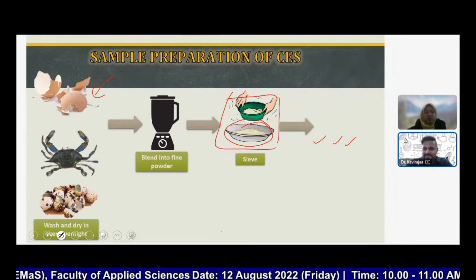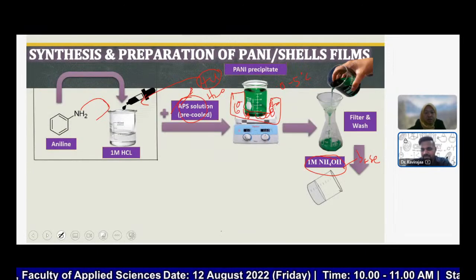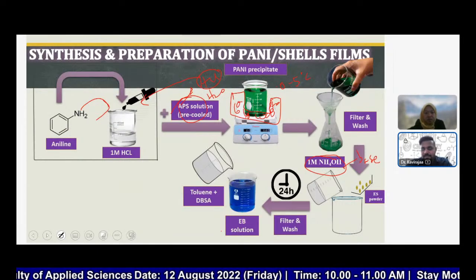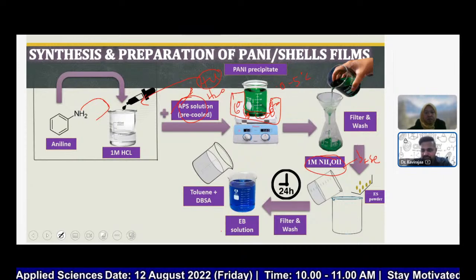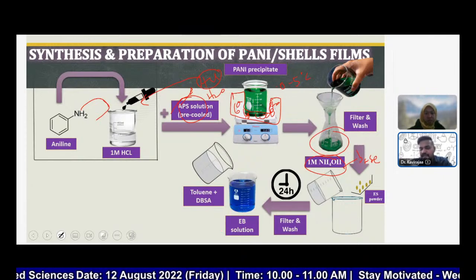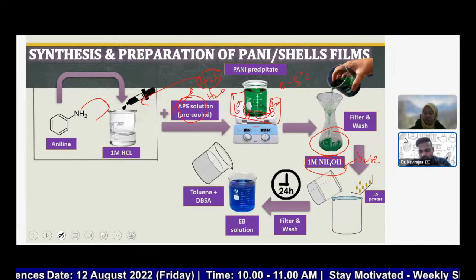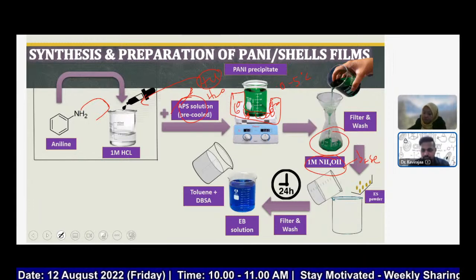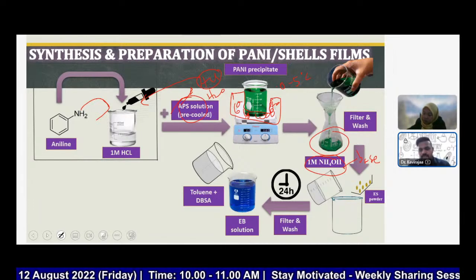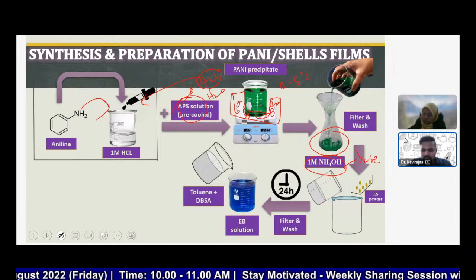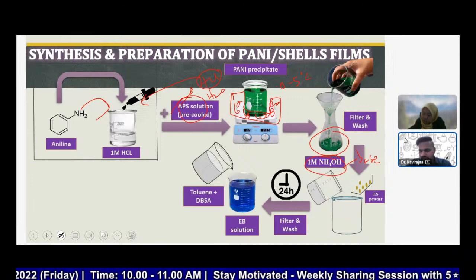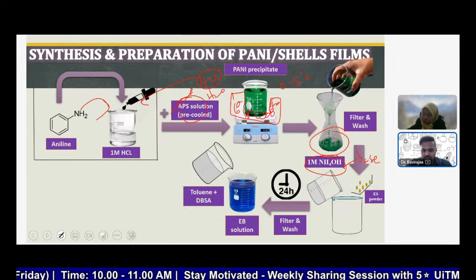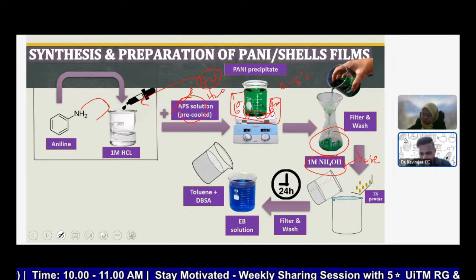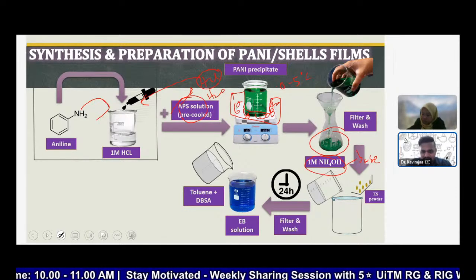The reason for that step is basically because when the polyaniline is produced, which is green in color, it might not have uniform polarons or dopants throughout the polymer backbone. So when we de-dope using ammonium hydroxide, we let it immerse for 24 hours as well, and then we will get a blue color solution. So we will filter it.